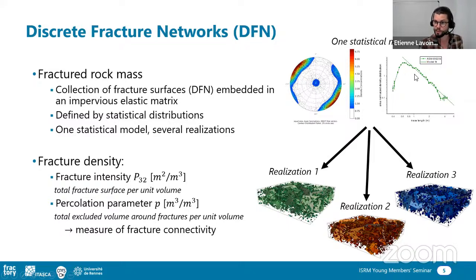So here you can see the size distribution that is fitted by a power law model, meaning that you have a lot more small fractures than large fractures. And once you have this statistical model, you need to perform several realizations to quantify the uncertainty associated with such a model. And one of the most important things to consider with fractured rock mass is the fracture density. And depending on the process at hand, it may be relevant to use different ways to quantify this density. In 3D, the two main ways to consider density are fracture intensity, which we call P32, which is defined mathematically as the total fracture surface per unit volume.